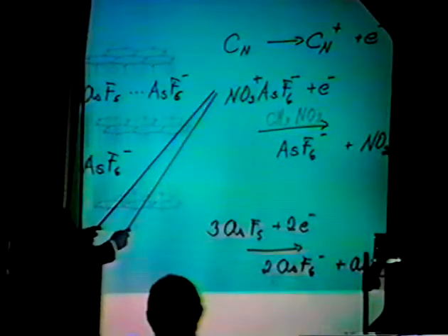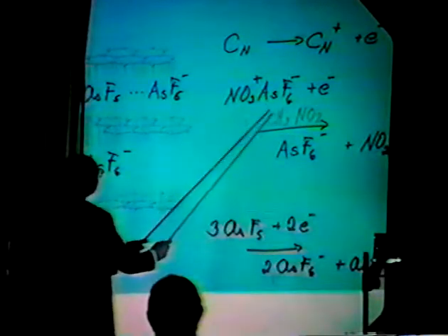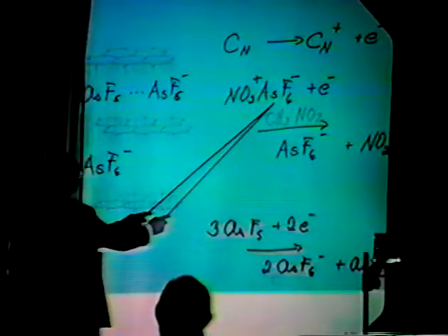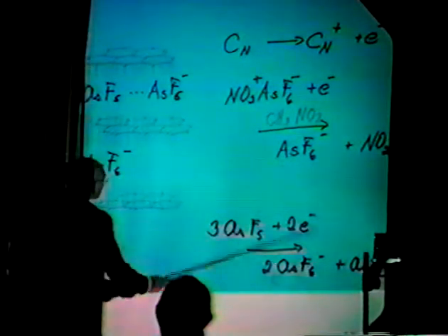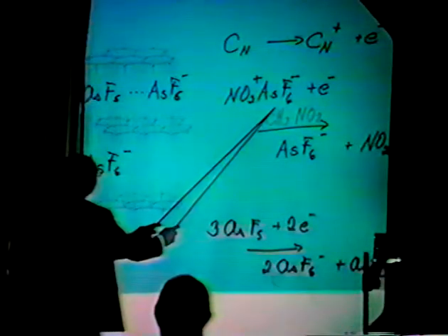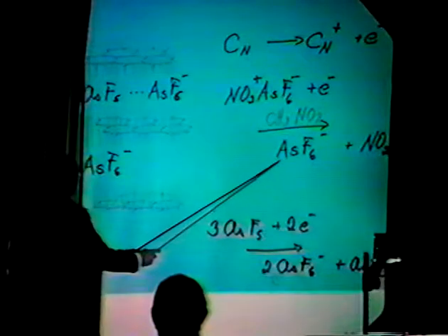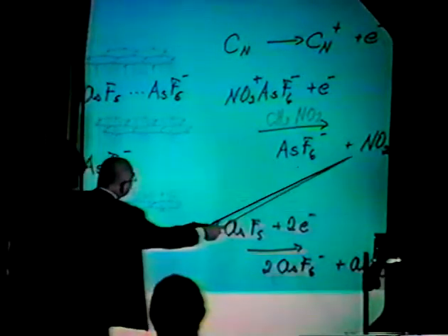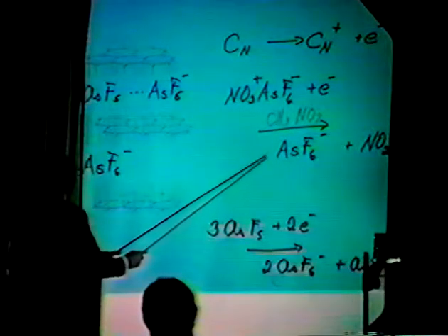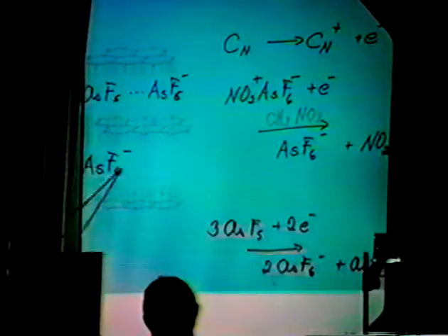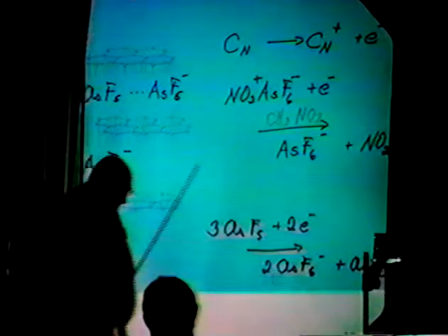We can also use other reactions. If you want to put just AsF6- and not have this mixture of things in there, we can use this reagent. React with graphite, and we put AsF6- in there. The NO2 goes off as gas, and unfortunately, a little bit of nitromethane goes into these graphite layers as well. So, what happens when I do this intercalation?